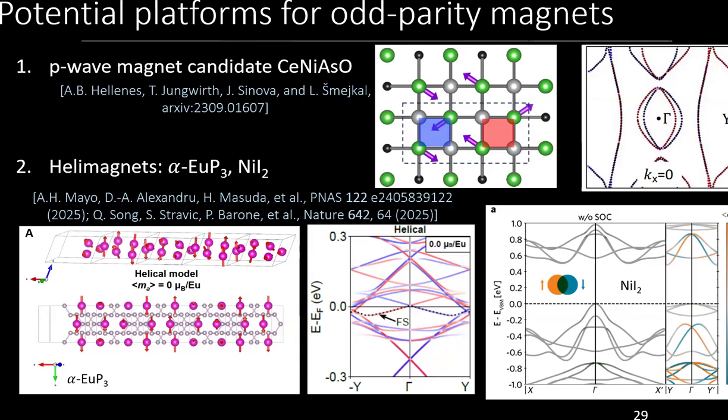So mostly the workflow of people now is to use symmetry groups to classify materials, and by symmetry groups identify which material may show altermagnetic quantities or not. Then try to perform DFT and determine whether the material is stable or not. DFT is also actually pretty bad because there was a case of ruthenium oxide where people predicted by DFT that it is an altermagnet, even measured it to be an altermagnet by some wrong technique, but then it was proven to be non-magnetic. So it's symmetry, DFT, and then experiment, preferably ARPES or transport or a combination.